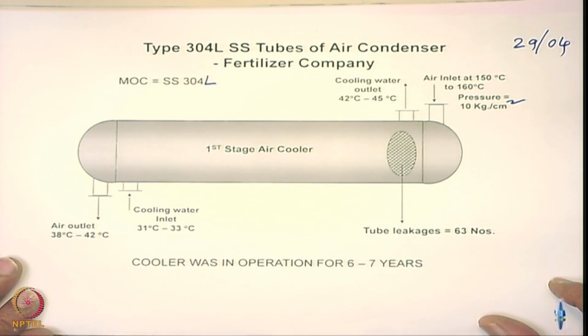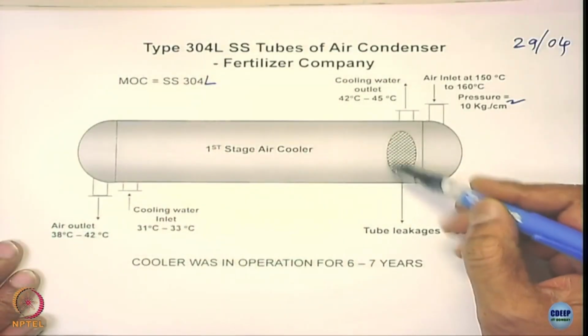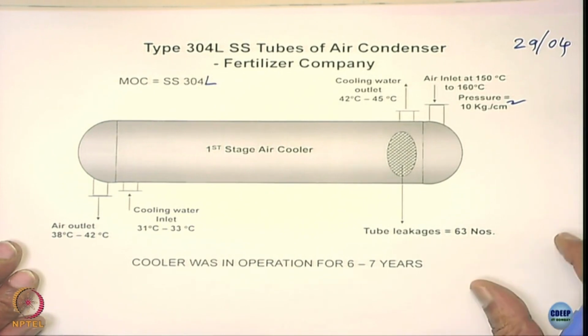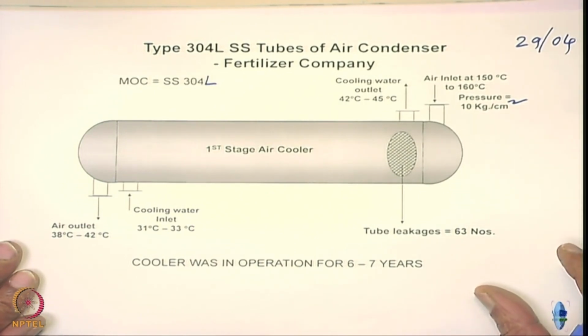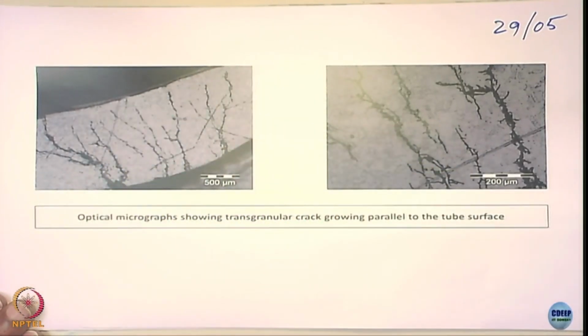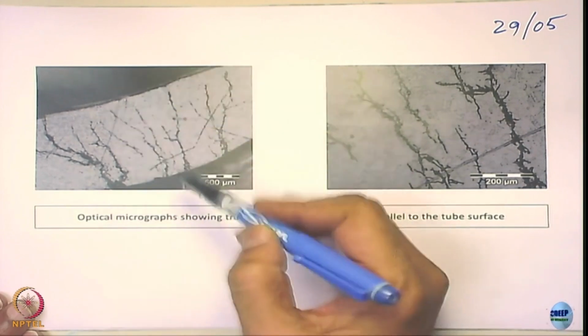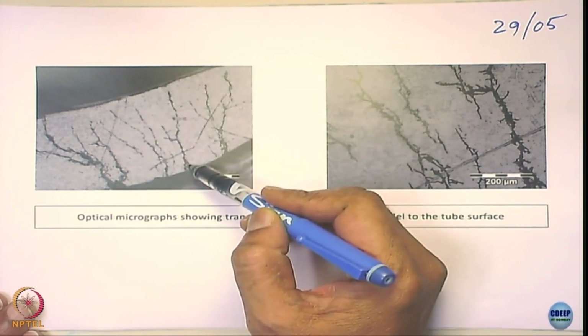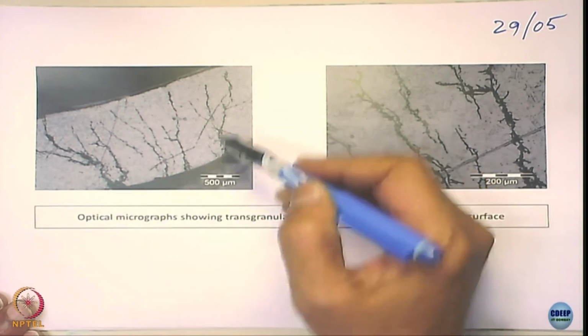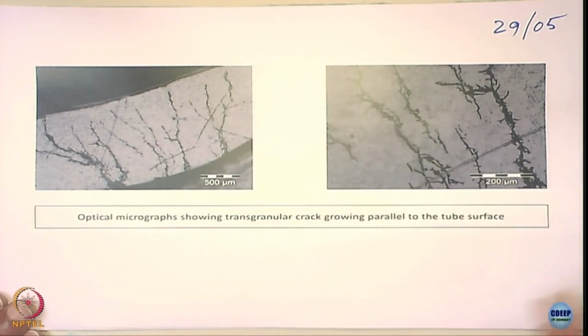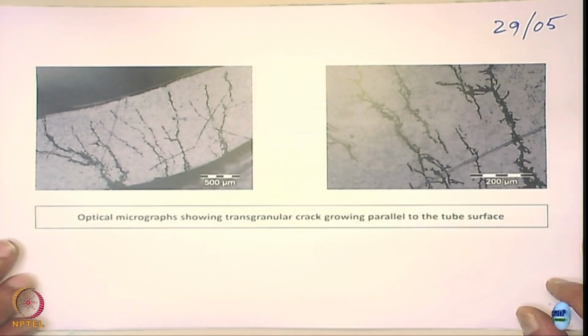The material used was 304L stainless steel, it is a fertilizer company, and the cooler was in operation for 6 to 7 years, not longer. And the tubes which are inside, 63 of them started leaking actually. That was a problem. So they are all premature failures, right. You just take these tubes and see the tubes in a microscope. This is the cross section of the tube. You see here the crack started from the external surface where the water went through, okay. So because the surface is covered with water, you start cracking. This is called cooling water. This is not a distilled water. It is of course an impure water, not like your DM water.